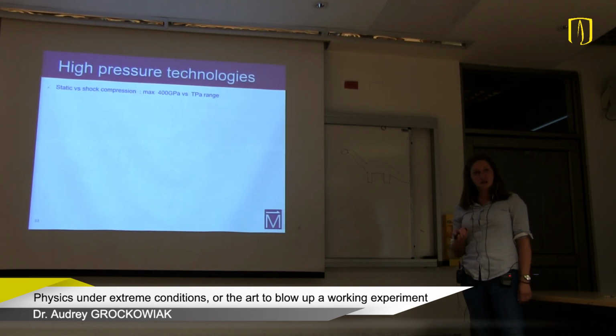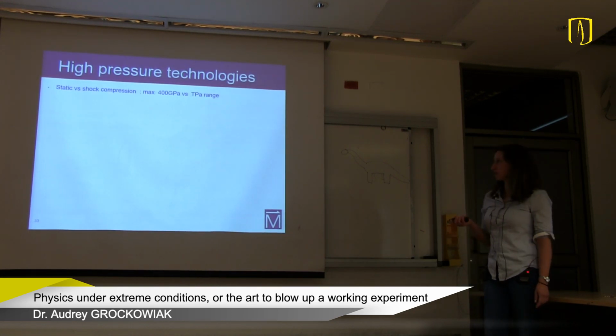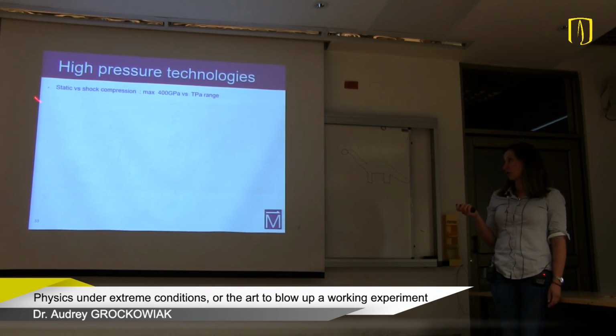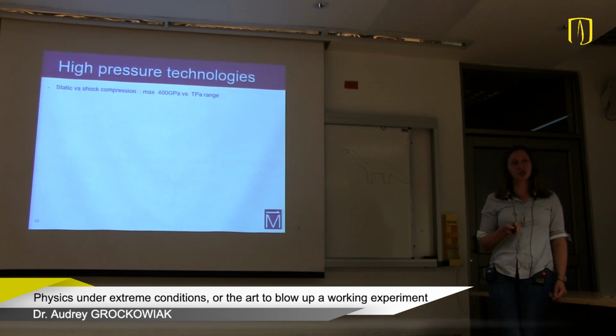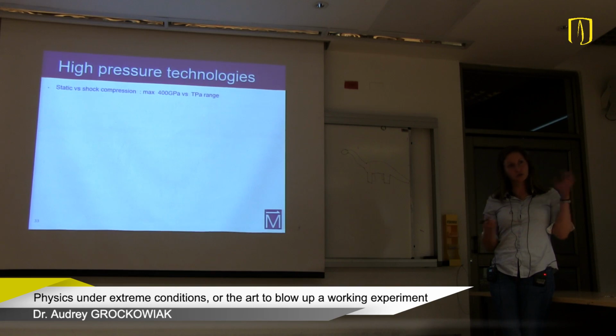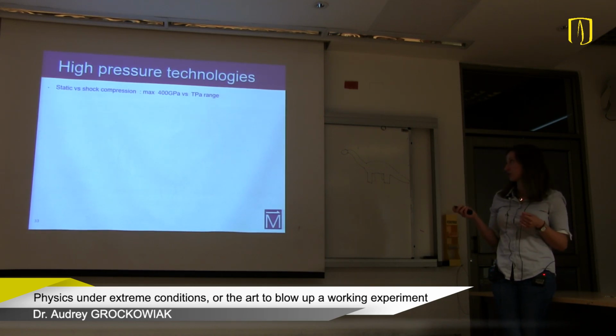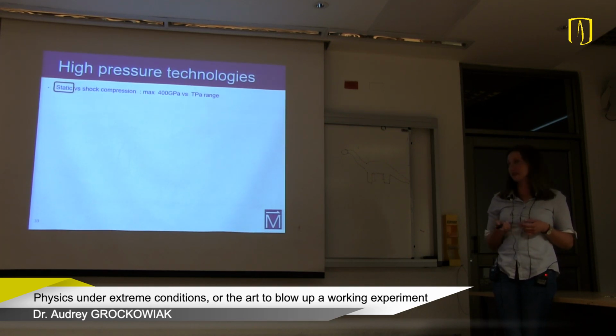So there are different ways to do high pressure. First you have to decide whether you want to do static versus shock compression. Either you want to put your sample under high pressure and keep it under high pressure, or create a shock wave that will basically destroy your sample, but you can go to much higher pressure. You can go to a maximum of 400 gigapascal to the terapascal range for shock compression. And this is a completely different business. So I'll speak here only about static high pressure.